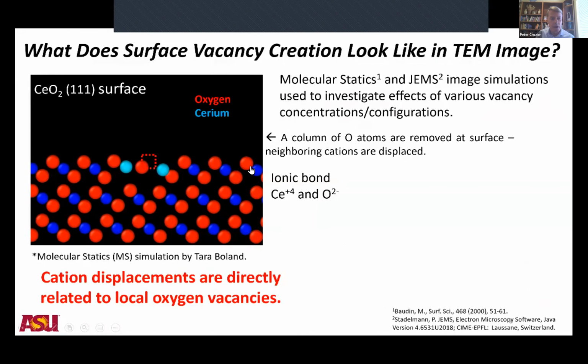We did some molecular statics because we know that, of course, ceria is ionically bonded, and this is just a cartoon of a surface. The cerium atoms are shown in blue, the oxygens are red, and the ceria are blue. What my student Tara Boland did was pull an oxygen out of the surface, creating an oxygen vacancy. And of course, because of the ionic bonding, when you pull that oxygen out, the structure relaxes.